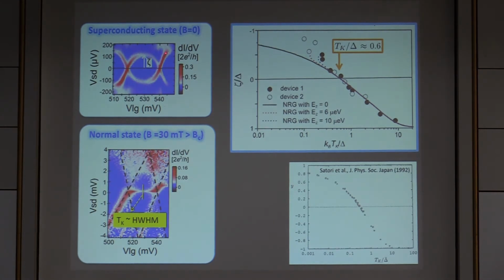So we also measure the energy level of the Andreev states as a function of this dimensionless parameter, the Kondo temperature over the superconducting gap. So you see that if the Kondo temperature gets very large, it means that our coupling becomes very strong, so we favor a singlet ground state. Whereas if our coupling gets very small, so this parameter decreases, we favor a doublet ground state. And there is this phase transition that occurs at this ratio of T_K over delta, which is in good agreement with old predictions from Satori et al.